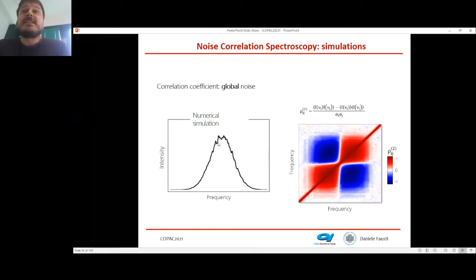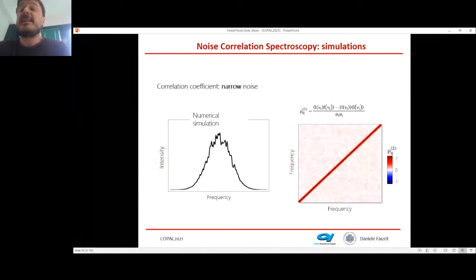On the other hand, if I have frequency fluctuations, what do I expect? I expect negative correlations between frequencies which are on one side and frequencies which are on the other side, because if for a given realization the frequencies on the right are above the average, the frequencies on the left are below the average. So I have these negative correlations between frequencies on opposite sides. And the most interesting situation instead is the one where I have frequency uncorrelated fluctuations, so that one frequency correlates only with itself and doesn't correlate with anything else.